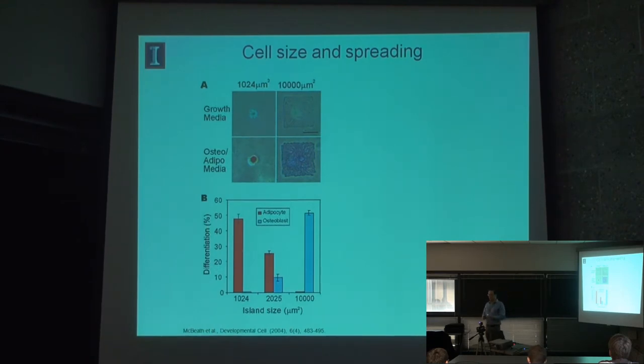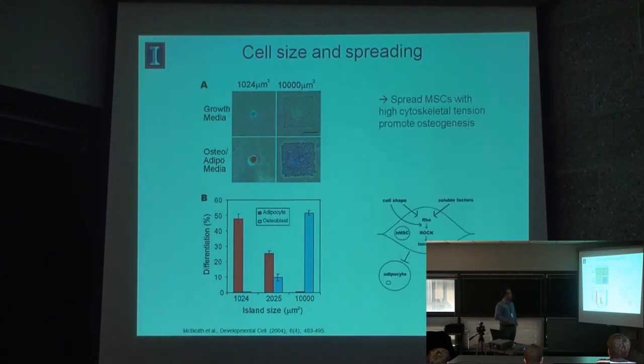And so clearly, the spreading of these cells is important for differentiation, and it makes sense in terms of other observations made with other material systems, which show that when a cell is very well spread on a nanostructured surface or on a stiff matrix, they prefer to differentiate to bone than if they're balled up or rather spindly. They did some really nice, elegant work to show that this involved signaling pathways that utilized a feedback loop between RhoA, a small GTPase, as well as Rho kinase, and that in the absence of high levels of RhoA, cells would prefer to turn into fat.